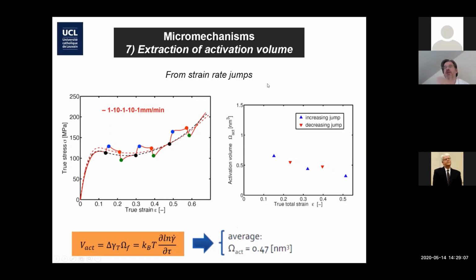And then we perform other kinds of activation volume measurements, and I will explain later what is activation volume. I think many of you know that. You have here on the left, we perform strain rate jumps. So during a compression test, we suddenly increase the rate, then continue the test, then decrease the rate, continue the test, re-increase the rate, so jumps of strain rate. From that, you can take the derivative of the stress with respect to the derivative of the strain rate. And based on that, you can extract the rate sensitivity exponent, but also a parameter named the activation volume. And the exact definition is given here.